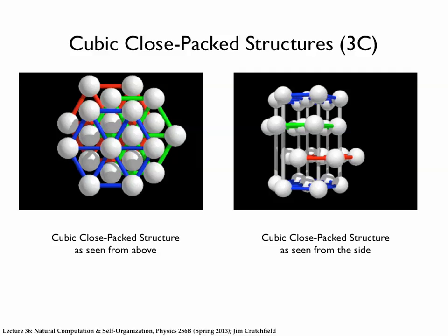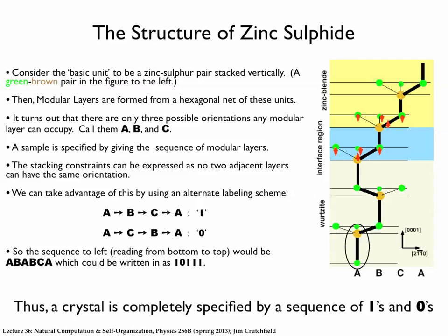So we're going to talk more in depth about the structure of zinc sulfide, but this title doesn't necessarily have to be zinc sulfide. There are a number of materials that stack this way, and silicon carbide is certainly one. So our basic unit layer now, the orange that we looked at, when we look down on it, we have to think that it's really two atoms, and in this case it is a zinc and a sulfur atom, and they're separated by a distance. Each atom of each kind is tetrahedrally bonded to four atoms of the opposite kind, and it stacks up to make a lattice this way. It's not completely obvious when you look at it. You have to think about it, at least I do.